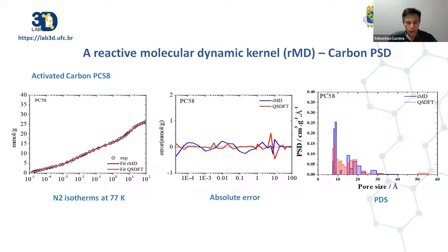Now we analyze again the activated carbon PC58, previously presented in the multi-kernel section. Our reactive kernel presents a perfect fit between experimental and simulated isotherms. Just like the quenched solid DFT, with the naked eye, we can't see a difference between the two models.